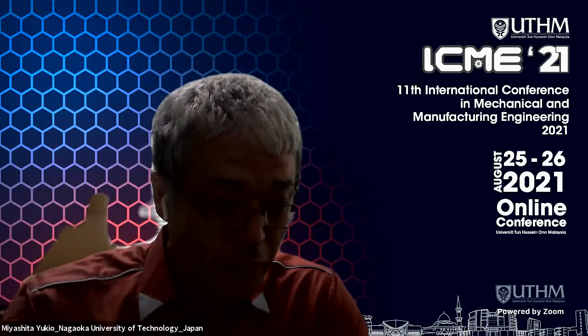Okay. The second one is aluminum content. Aluminum has many meanings. But one is that if you put aluminum into magnesium, intermetallic will be formed. That intermetallic is in some cases important. I mean, the intermetallic is usually very hard, so you can improve the mechanical property by adding the aluminum content. But at the same time, those intermetallics can be the fracture or fatigue origin.